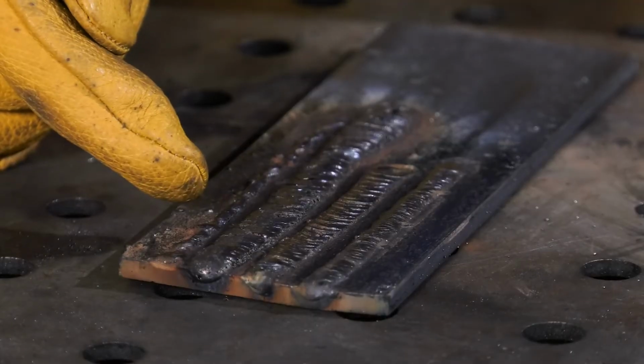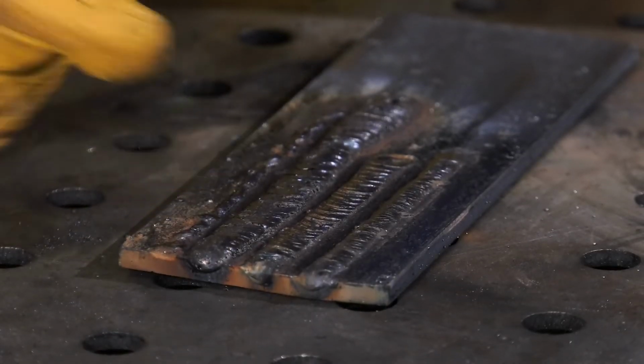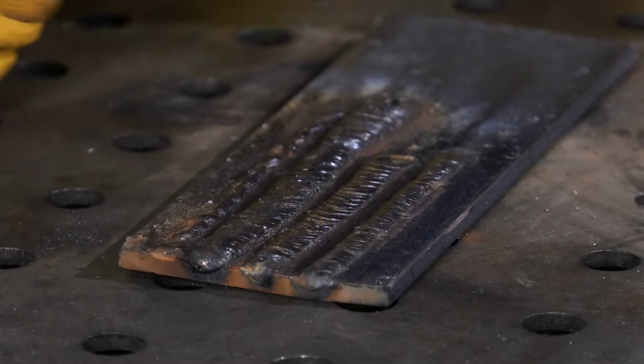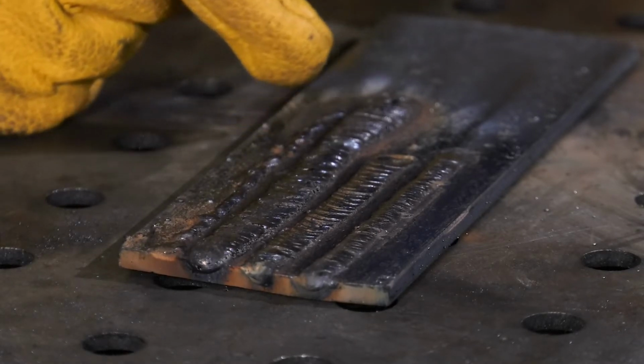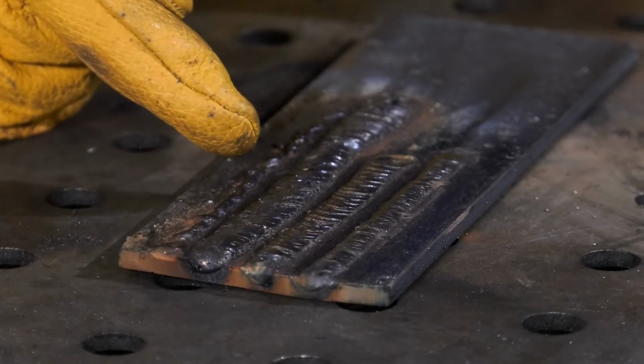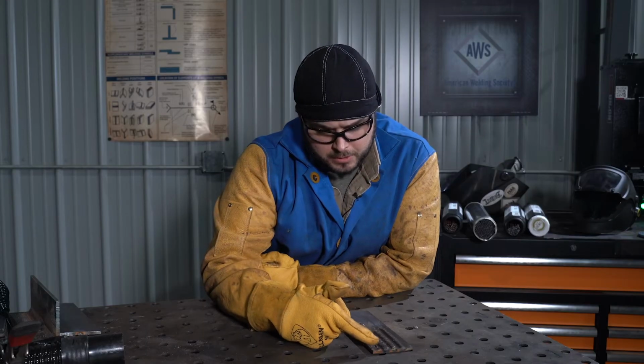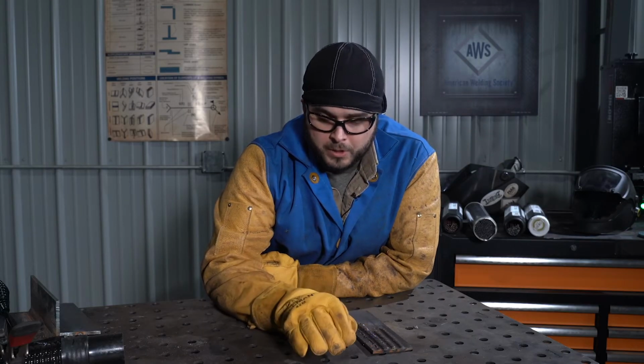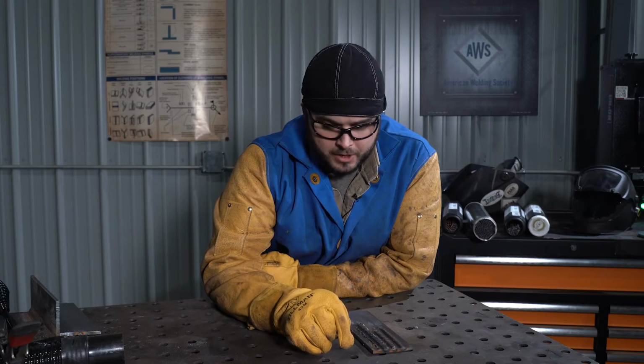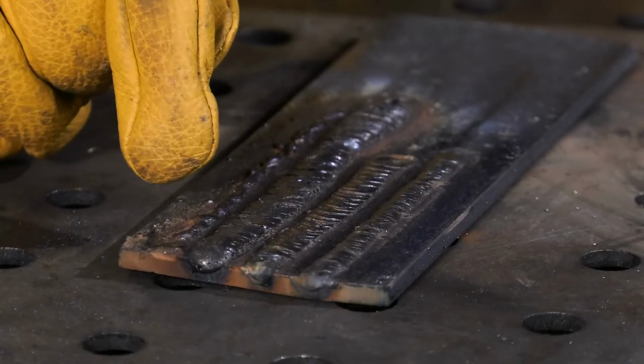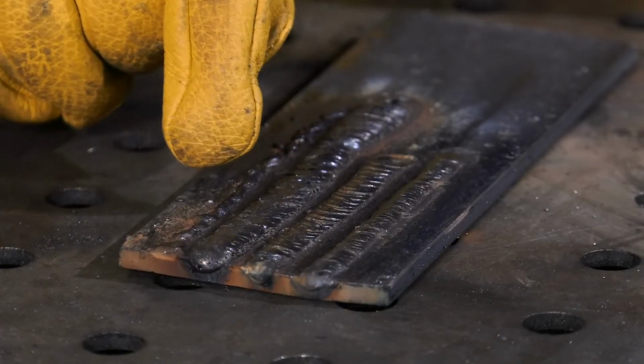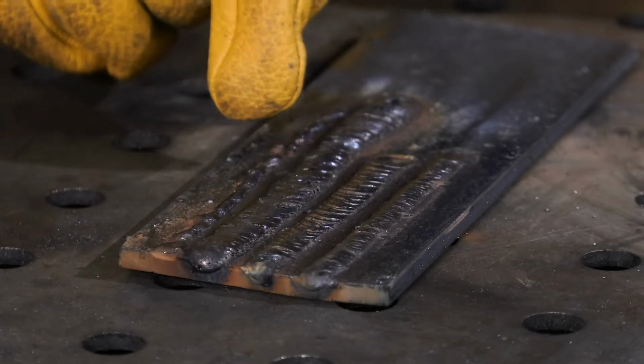Two, travel speed. Too fast. Very narrow bead, tall profile, sometimes very inconsistent along the toes of the weld, and undercutting will be present. To remedy this, slow down. Let that weld pool build up, increase in diameter, keep that arc length nice and tight, and let that pool just kind of work its way across so that it's nice and uniform.